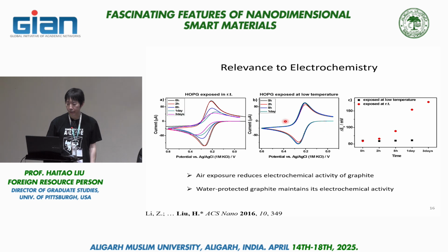Again, more on this. But if you compare those two data, you find if we expose graphite to room temperature, we see this degradation pretty fast. But if we keep it at low temperature, and the intention here is to trigger a condensation of moisture on the surface, we can maintain the electrochemical activity pretty well, even after a day of exposure in air. So there's some hope of maintaining the electrochemical activity by very simple manipulation of environment.